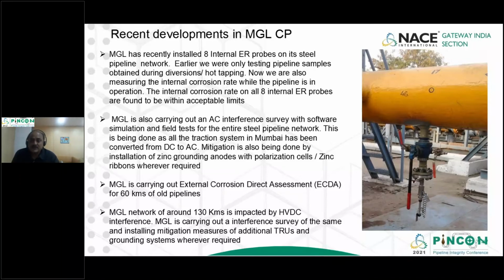Now we have the internal ER probes installed in our network, and we measure the internal corrosion rate while the pipeline is in operation. The internal corrosion rates for all the ER probes which we have installed, we have found to be within acceptable limits, which is 8 MPY. We are getting below 1 MPY as such.